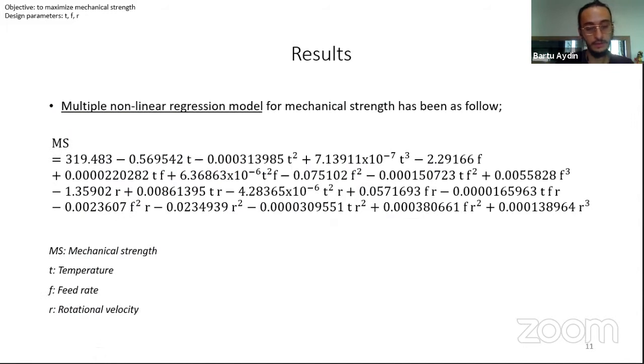By using training data, the multiple nonlinear regression model for mechanical strength has been obtained as follows. And this is a third order model function, and you can see at the bottom that temperature is represented by T, feed rate by F, rotational velocity by R, and mechanical strength by MS. This is our objective.